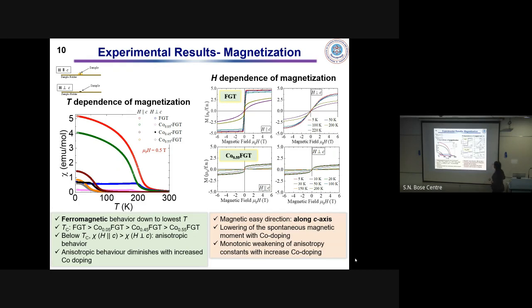Okay. So now here you can see one of the MH curves for one of the doped samples, and for all the doped compounds we could see that there is a lowering of the spontaneous magnetic moment with cobalt doping, and also a monotonic weakening of the anisotropy constants with increasing doping. We calculated the anisotropy constants also, which are not shown over here. There was a monotonic decrement.